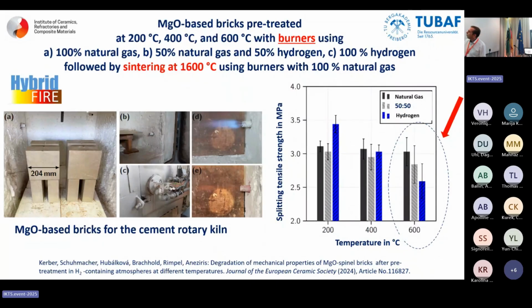What we have seen is, pay attention, above 400, especially above 600, we lose more than 40% of the strength, based on the splitting test. And you can imagine this is something like a 7 to 8 kilogram brick, and after 1 week, you lose bricks in a rotary kiln. This is a disaster. I would also like to underline, pay attention, the 200 degrees pre-treatment with hydrogen gave us very high strengths. If you go to the paper, you will see, based on differential thermal analysis, that the peaks of the calcium silicate formation or changing, also the brucite formation, have been shifted a little bit. It's not only thermodynamics, it's kinetics and thermodynamics.